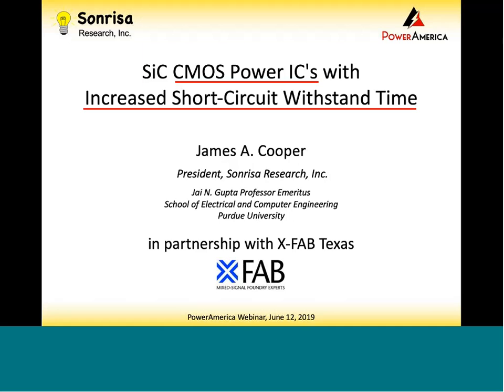The only place you might get into problems is if you get it too thin, and we don't know exactly how thick the transition layer is between silicon carbide and silicon dioxide. All indications from things like yields and XPS and so on are telling us that it's thinner than 2 nanometers. So we think certainly we can go down to 10 nanometers, and maybe even 5 nanometers.